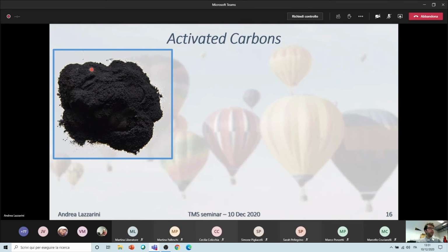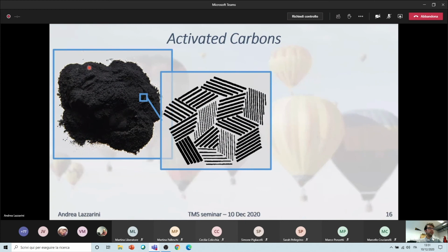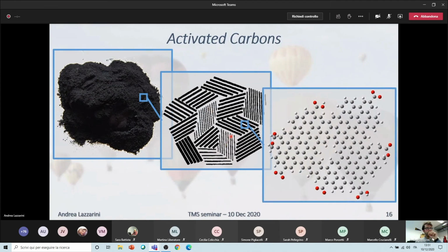But if you can go a bit deeper and get to know them a bit better, you can imagine a single grain of this dusty powder as an ensemble of different sheets made of hexagons that are characteristic of the graphite structure, basically disposed in a random way throughout the grain. And what is interesting is that going to this intermediate scale, to the nanoscale, so going to study each single one of these sheets of graphite/graphene, you can see that you can have a very large variety of functional groups and structural defects.